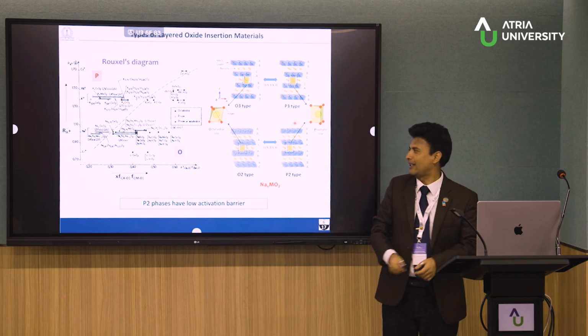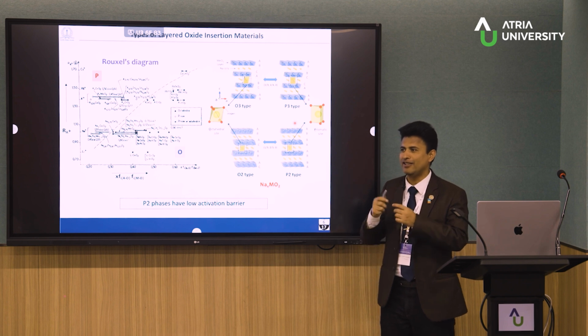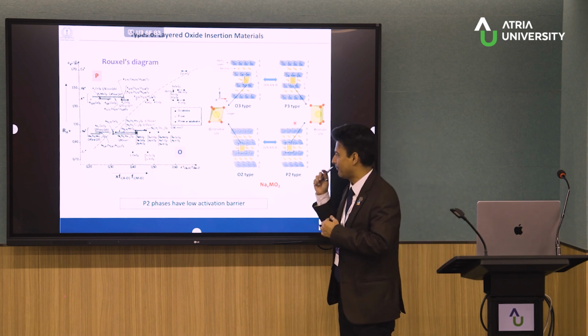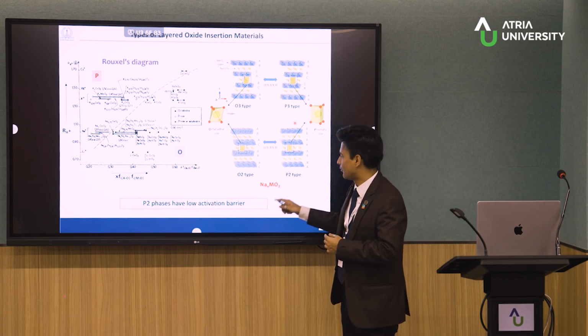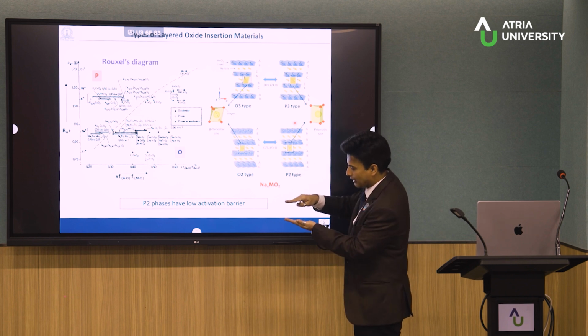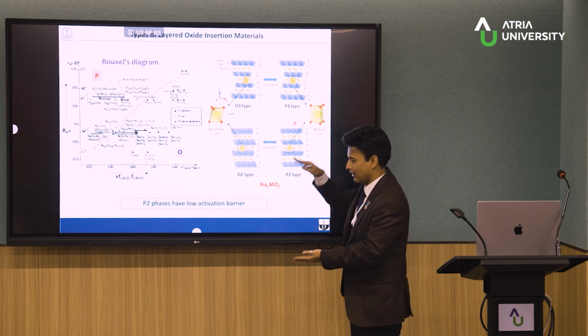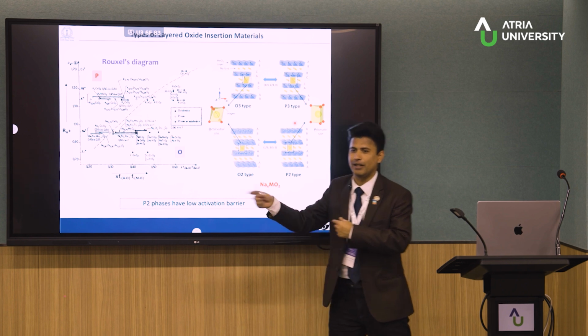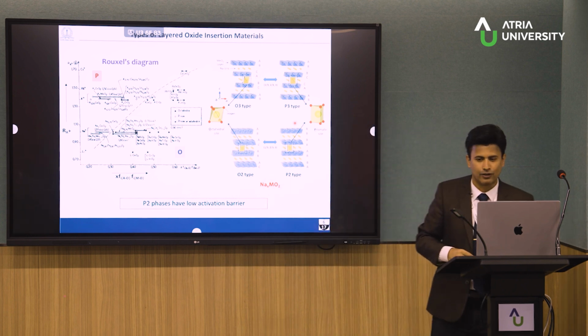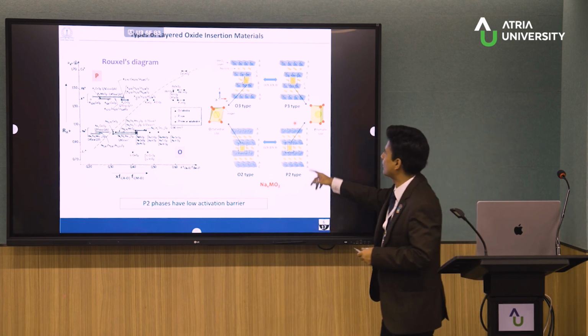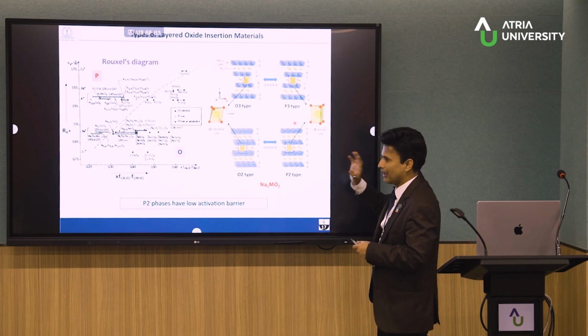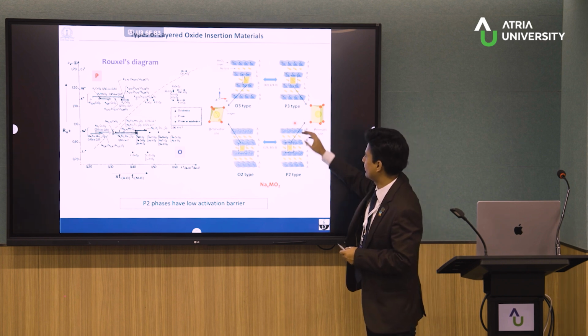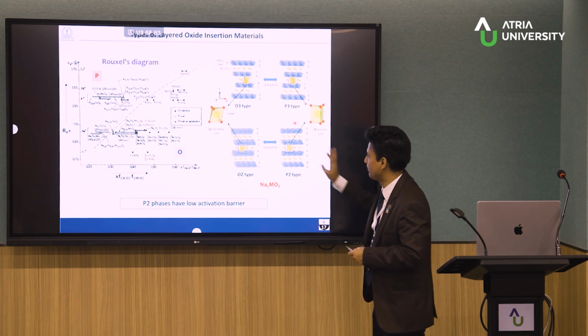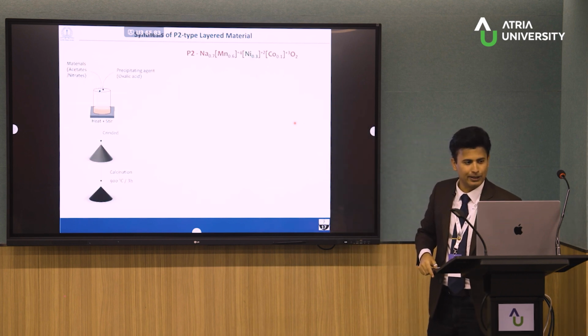So the rate kinetics in case of prismatic system in general is much better than the O kind of system. So basically, because the interlayer distance is high, activation barrier is very low, so ion mobility is very, very high. That's why people try to move for this P kind of system, P3, P2. In real life, it is very difficult to make P3 kind of system. Many compositions are known for P2. So we will talk about this P2 system.